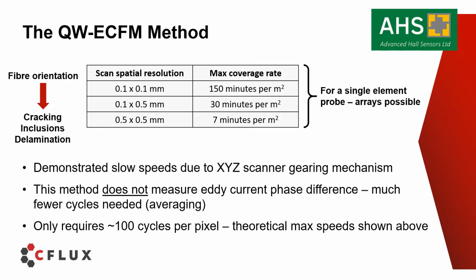This is because we determine the amplitude of the magnetic flux density generated by the eddy currents formed on and in the carbon fibre sample. As such, we require a lot less averaging than other methods which require determination of phase shifts. As such, we can achieve coverage rates of between 7 and 150 minutes per square metre, depending on the spatial resolution required, the type of flaw, evaluation necessary, and NDT context.